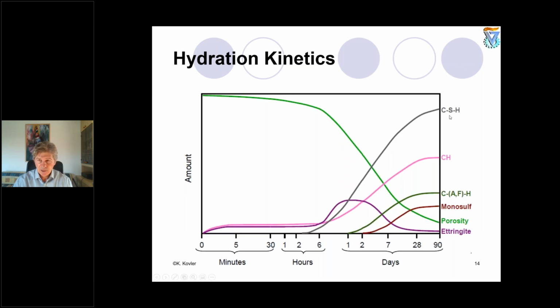This calcium silicate hydrate phase is the decisive phase of the strength. It's a strength-bearing phase, but it doesn't form very early, so it needs some time. The first period is called the dormant period, when nothing has happened. It's because of the need to regulate the setting times to provide a possibility to work with fresh concrete. I'm speaking about transportation, casting, vibrating, finishing, all kinds of technological operations with very fresh concrete. Strength starts growing a few hours after the so-called setting time. But I don't want to go into details now. We have different setting times, initial set and final set, but in principle we are speaking about hours and then days.